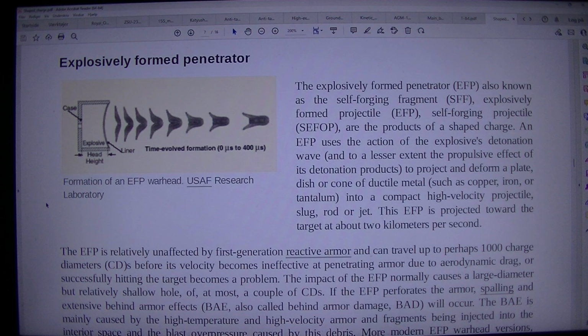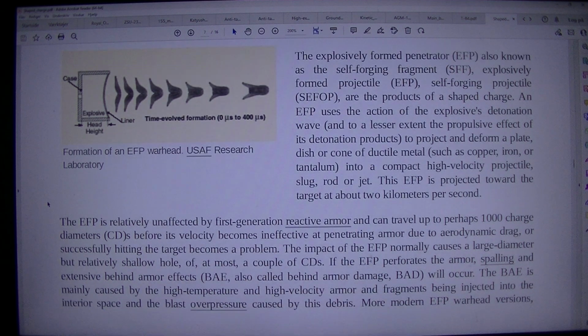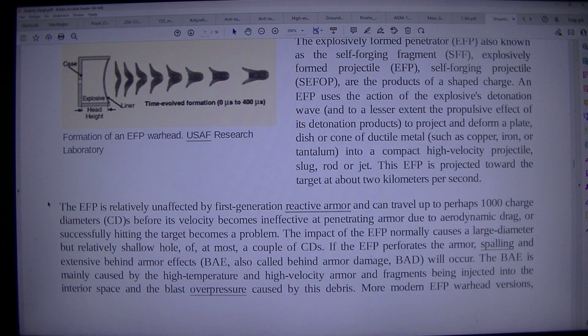This EFP is projected toward the target at about 2 km per second. The EFP is relatively unaffected by first-generation reactive armor and can travel up to perhaps 1,000 charge diameters, CDs, before its velocity becomes ineffective at penetrating armor due to aerodynamic drag, or successfully hitting the target becomes a problem.